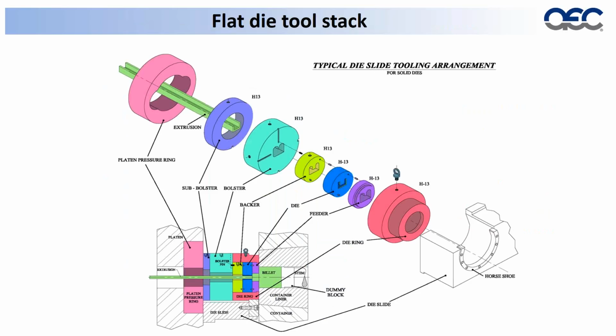The horseshoe is the same size as the die ring, and inside the die ring goes the die and the backer. And there is this little purple thing there called a feeder, which we sometimes use. The die and backer sit against the bolster, and that is the tool stack. And that tool stack has to withstand all of that load that's coming from the press and not deflect. So it's quite a challenge, but it's far from impossible. It's just one of those things we have to manage.